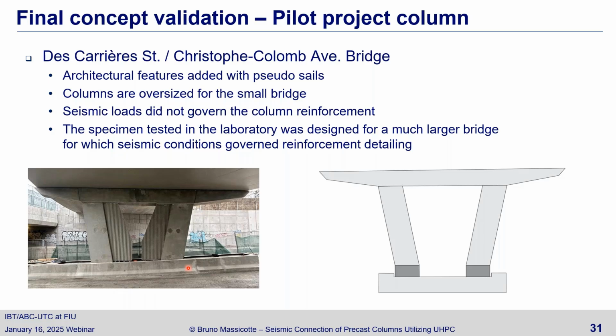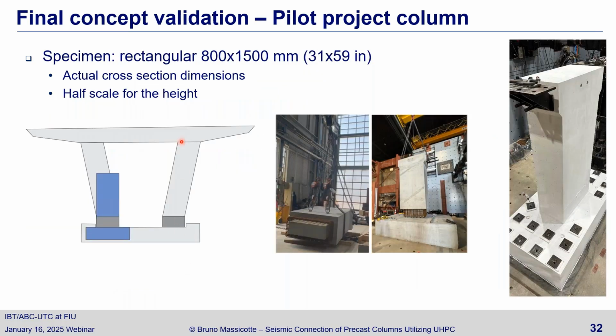So those columns that we tested were not larger, but had capacity for seismic design for a much larger bridge. Because of the size, this is about 20 feet here, where the lab space is a bit less. So we tested a column that was close to half of the actual column size here, but we kept the same dimension, the same size of the column. So this is what we see here.